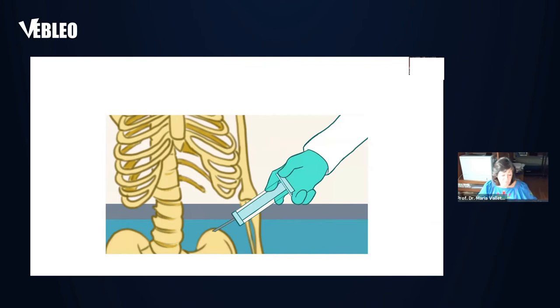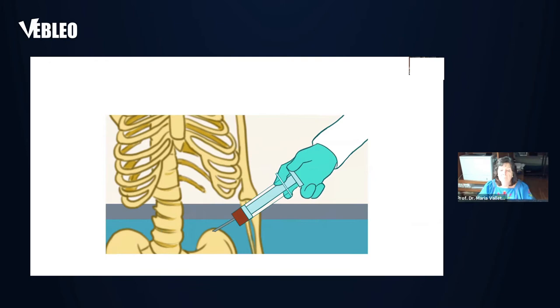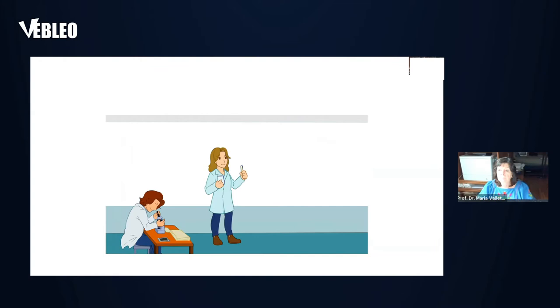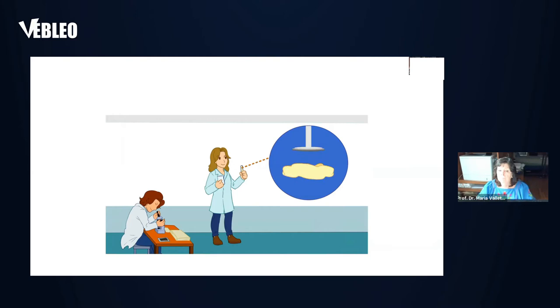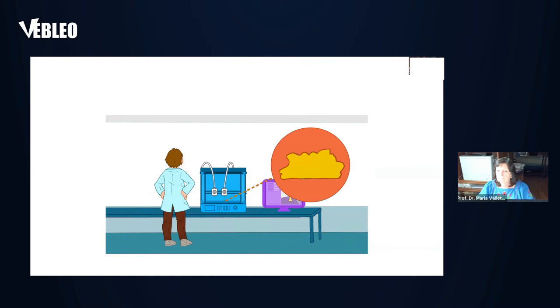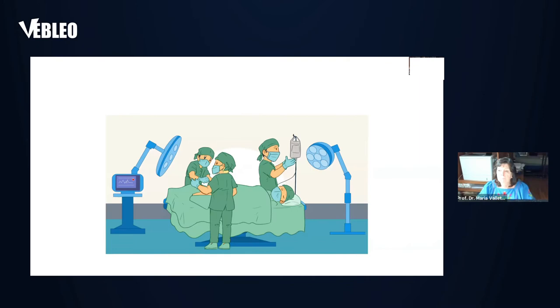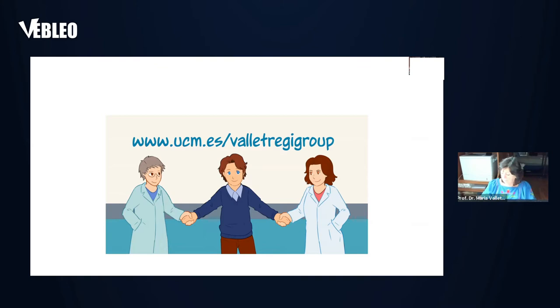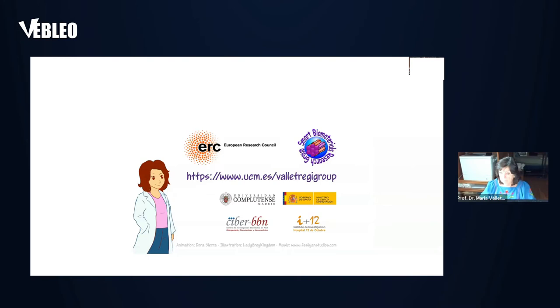These newly designed biomaterials ideally would not only regenerate the target tissue, but also supply mechanical support and prevent surgery-related infection. Different tissue engineering approaches aim to promote bone regeneration by using stem and pluripotent cell therapy. Bone tissue engineering implies the use of biocompatible porous templates commonly manufactured with bioactive bioceramics, calcium phosphates, bioactive glasses, which are osteoconductor and can be decorated with osteoinductive molecules that favor cell growth and differentiation. All these laboratory developments must benefit the patient. Thus, their emphasis must lie in translational research.